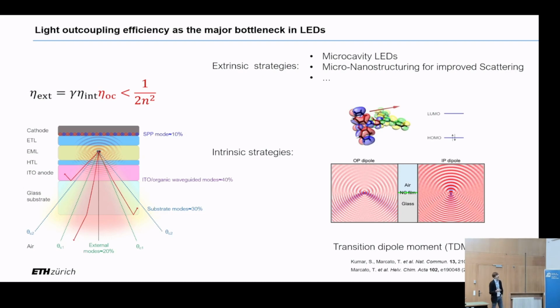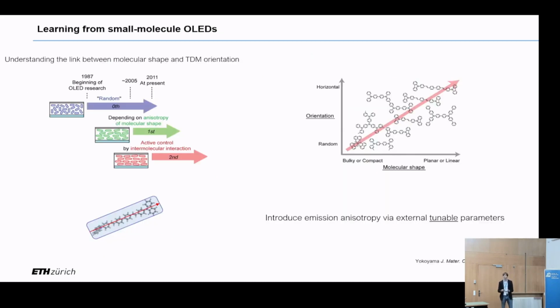And people soon realized that, well, if I somehow manage to orient such transition dipoles in the plane of an LED, for example, I would effectively maximize the light which is going out of the device, thereby enhancing extraction. And this has now been a staple of high-efficiency OLED, maybe for 10 years, across all the generations of OLED materials.